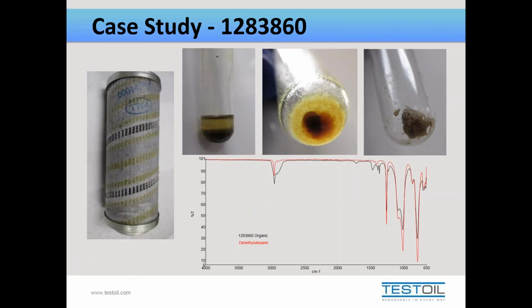So moving on to our next study, we actually have here a system that was using a hydraulic ethylene glycol water-based fluid. And this filter came from a filter loop that actually had a pump on the same loop. And the pump had failed, so we did expect wear metals to be present. So this customer actually had the filter debris analysis testing done first because they wanted to know exactly the metallics that were present from the pump and see how extensive the damage was. And we ended up finding iron, nickel, and chromium, and unfortunately the damage was quite extensive, it appeared.